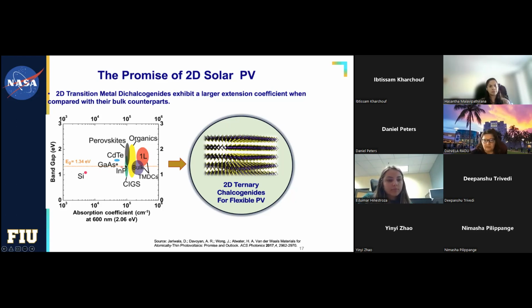If you look at these materials in this realm, CIGS and perovskites, if I go for one layer, I increase tremendously, almost on a logarithmic scale, the absorption coefficient. So I absorb more light if this material is at a very atomic scale. Okay, so this is a very attractive way. So the question is, can I transform that CZTS into a nanosheet material?